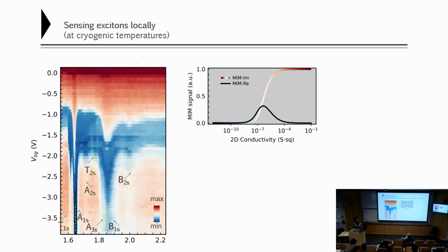Okay. But the overall trend of going through the band gap and going to the other side is still as expected. And the asymmetry on the two sides of the gap is due to the fact that it's a p-type. The asymmetry is mostly because of the tunneling process that can only happen for holes, not electrons, in the specific band alignment of hBN and molybdenite.